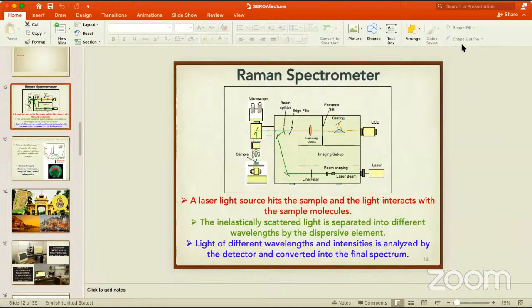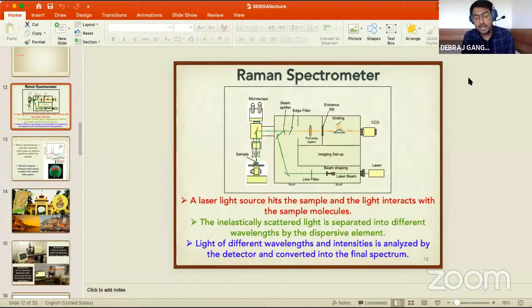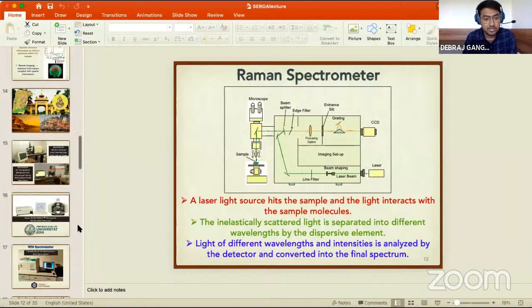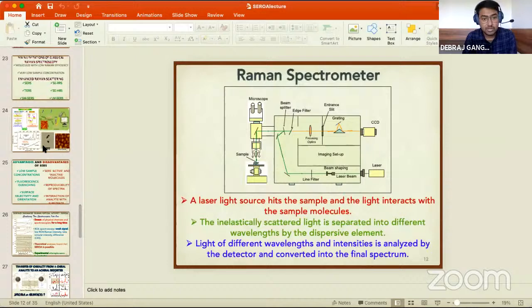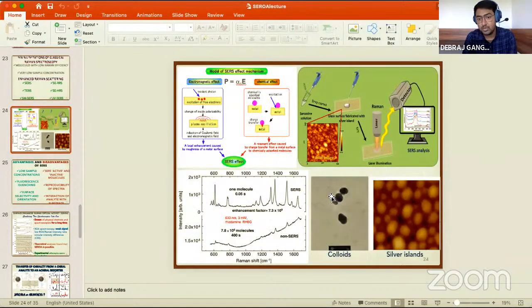What is the main difference between surface enhanced Raman scattering and tip enhanced Raman scattering? Okay, so both are enhancement techniques. In the case of surface enhanced, I have shown you, there are two kinds of substrates. One is the colloidal nanoparticles and one is the silver island film. On this film, we put the sample and then we put it under the Raman microscope and we observe the spectrum. Or we can observe it in colloidal nanoparticles.